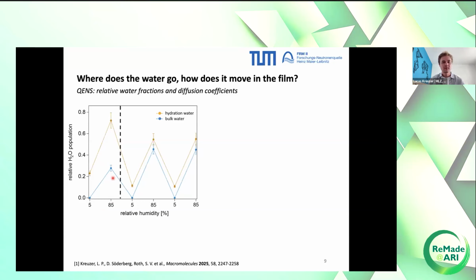And the second thing is that the first cycle of low and high humidity somehow differs from the remaining two cycles. So we start with a relatively high hydration water fraction, which then decreases in the second and in the third dry state. And the differences get even more pronounced in the humid state. We have a much higher hydration water fraction as compared to the other two humid states, but a lower bulk water fraction. So something is happening there.